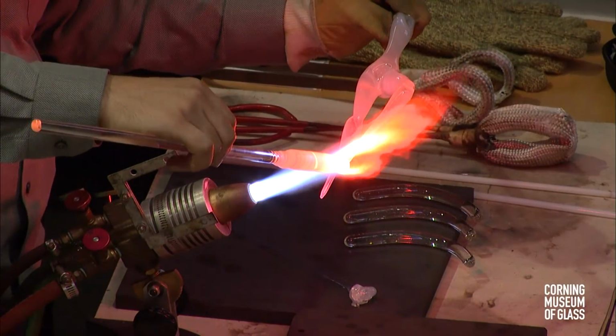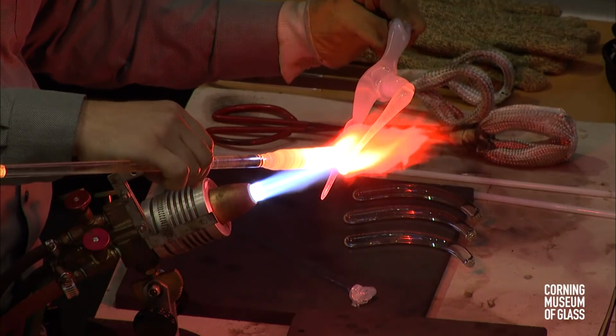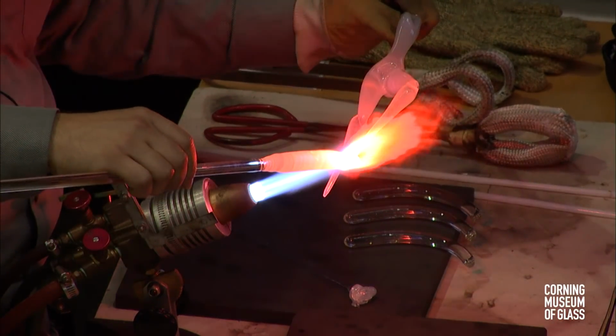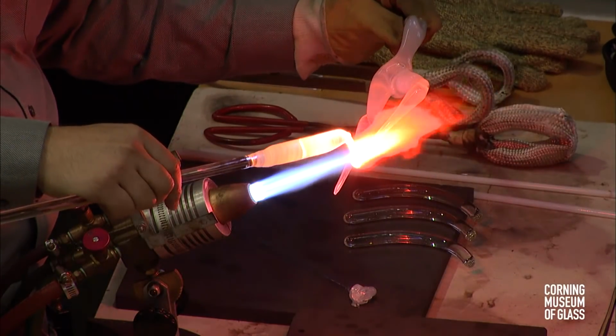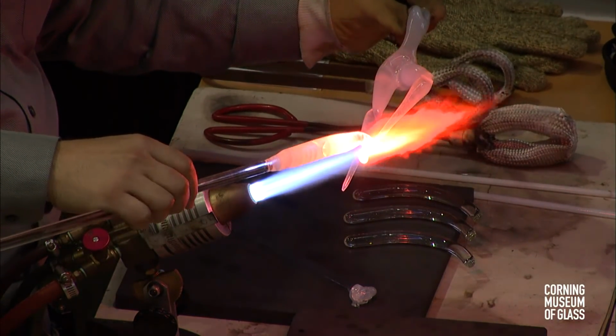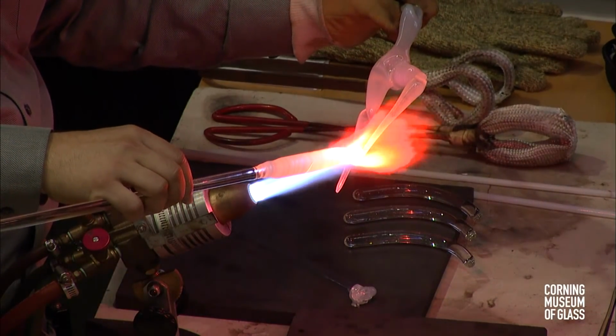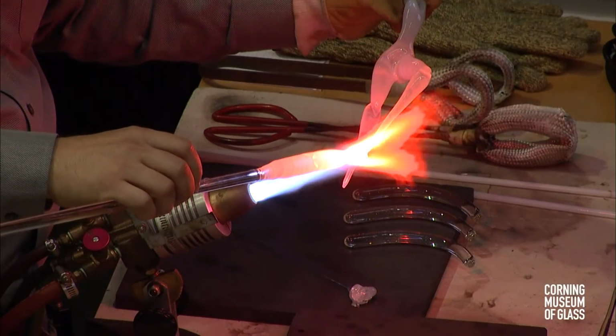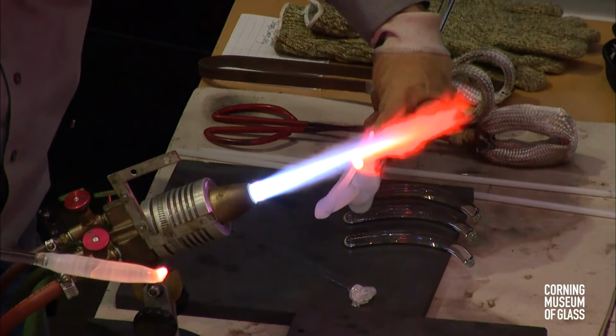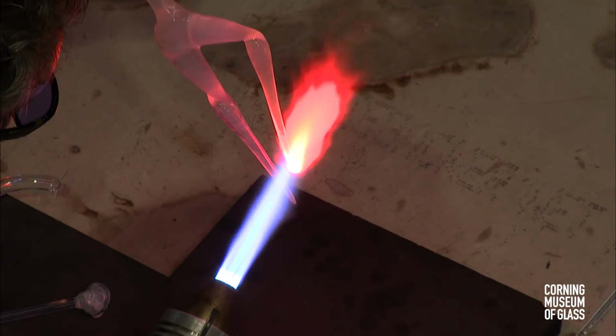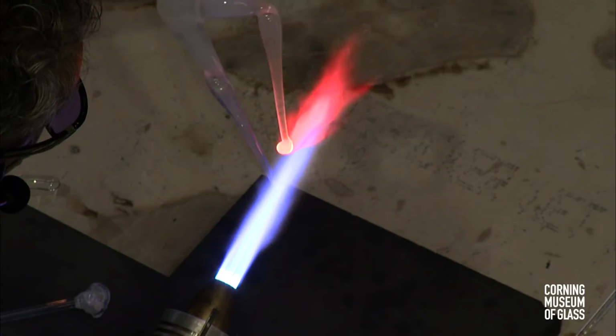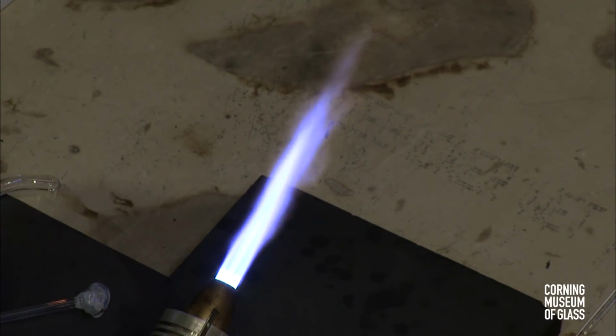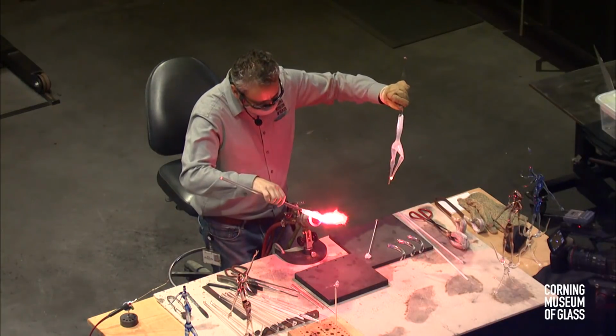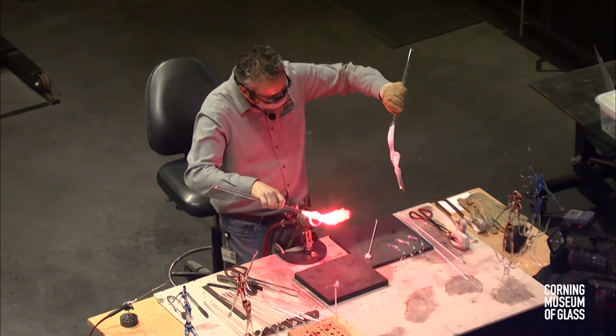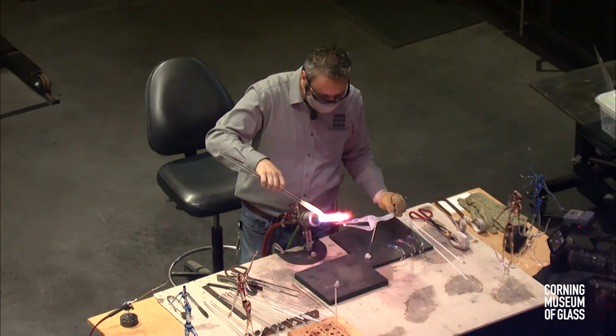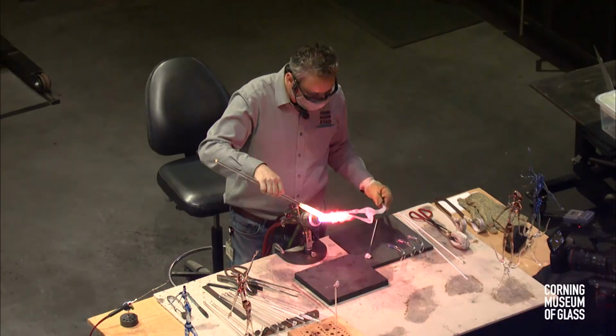And they found that by adding some boron oxide, they could in fact make a glass that expanded and contracted a lot less. And what that also led to was realizing that a glass like that would tolerate temperature change really well. Most glasses, if you heat or cool them too quickly or just unevenly, they tend to crack because they expand and contract so unevenly. But when you add a little boron oxide to it, it expands and contracts less, and it's less likely to crack just due to temperature change. We call that thermal shock.